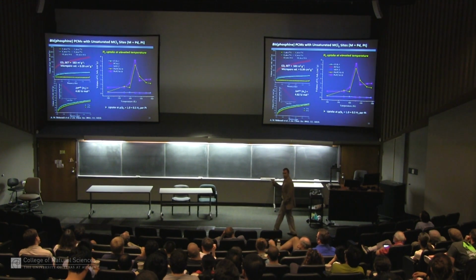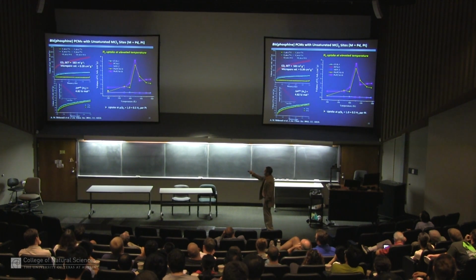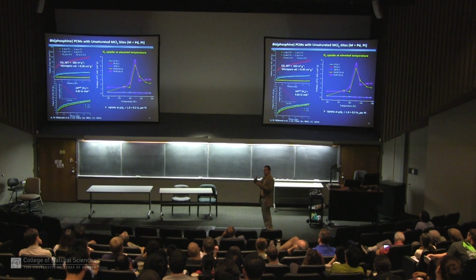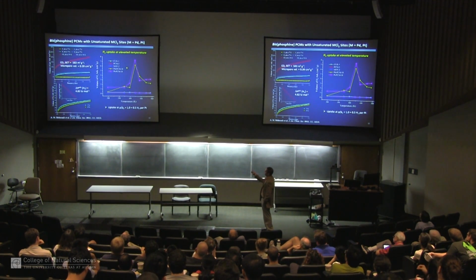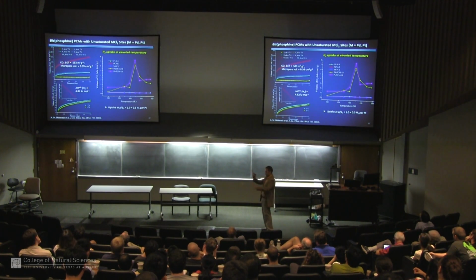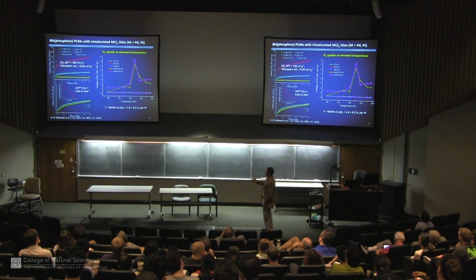And this hadn't been seen before in these types of materials, simply because, as you can see from these other sets of data, which are other known metal organic frameworks, the higher the temperature, the less the H2 wants to bind in the surfaces of the pores. It's just bashing around and getting kinetically too excited. We've got these reactive sites that grab hold of the H2, and some calculations since performed by a group in Berkeley have proven that it really is the H2 having an interaction with the pocket that's formed with this platinum or palladium site. We get trapping of the gases.